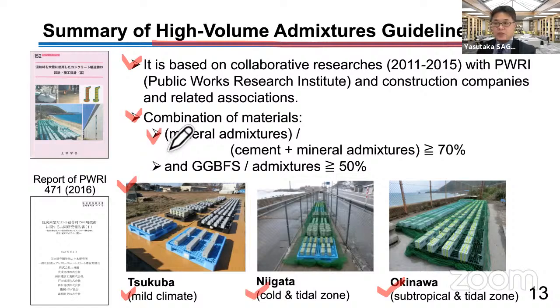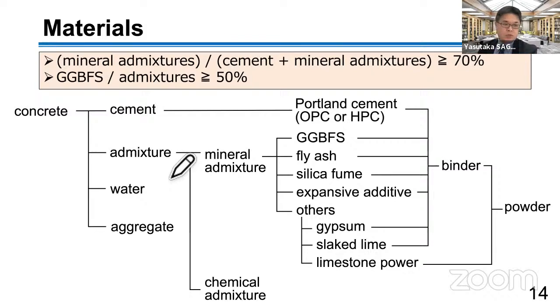The first one is the ratio of mineral admixtures to the total binder. It means cement plus mineral admixture should be larger than 70%. And the content of slag in the admixtures is larger than 50%. So it is a definition of high volume admixture concrete in this guideline. In this guideline, the mineral admixtures are categorized into blast furnace slag, fly ash, silica fume, expansive additives, and other materials. Other materials consist of gypsum, slaked lime, and limestone powder.